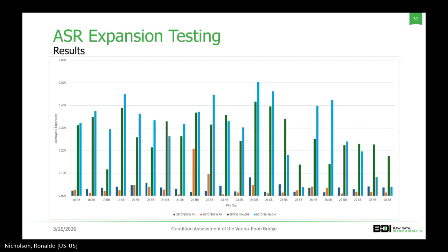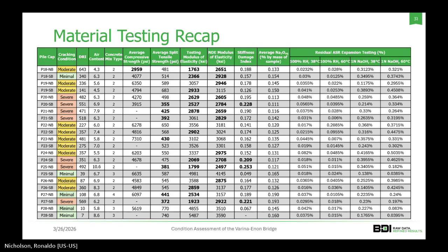I believe these results were primarily used qualitatively to evaluate the severity of the ASR in these concretes. But at the same time, I do believe that Dr. Sanchez used primarily the 38 degrees C with the sodium hydroxide solution for his models. Next slide, please.